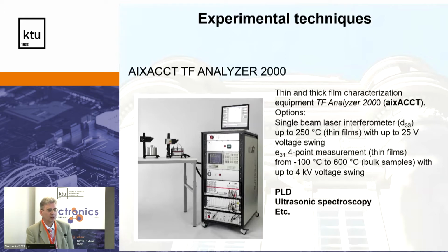So this is for energy harvesting. Then you apply an electric field or you apply tension and you see which current or voltage you are producing. And of course, to measure d33, all piezoelectric properties of the material are possible. And also for ferroelectric materials, and to those who do not know, ferroelectric materials are the materials which spontaneously polarize, and the direction of polarization is possible to change with an external electric field. So it's possible to measure hysteresis loops.